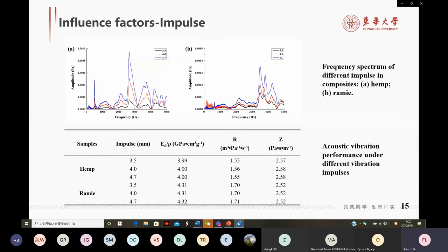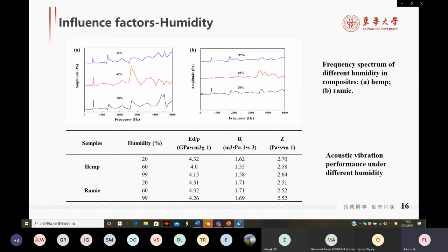The resulting acoustic spectra after impacting were similar, and the characteristics at the wave frequency were very uniform. Only as the pressure increased, the amplitude shows an apparent trend. The two composites were pre-measured in advance. The humidity was set to 20%, 60%, and 99%, the time for 24 hours, and the performance of acoustic reaction test after the humidity adjustment were complete.